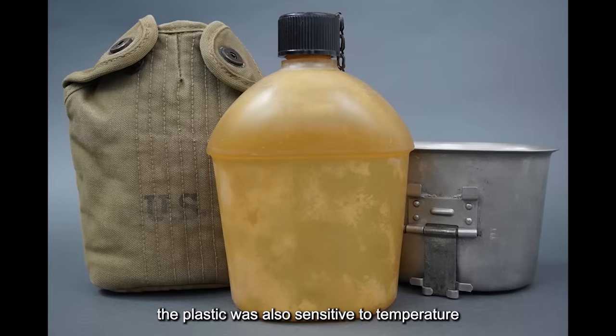The plastic was also sensitive to temperature. When exposed to heat, it softened. When water was introduced to sterilize the canteen by boiling, the plastic deformed. The canteens developed other problems. Heat stress cracks appeared. If the contents froze, the plastic shattered. The material was unsuitable for heating water over a flame, eliminating one of the canteen's key tactical uses. Alcohol in concentrations of 50% or higher attacked the plastic and destroyed the canteen entirely.